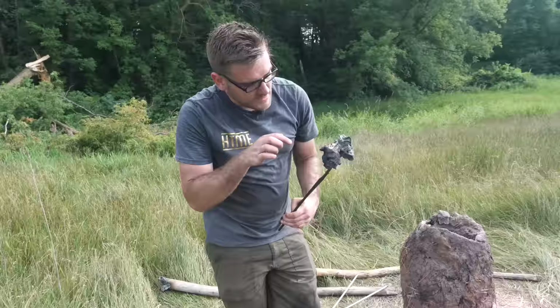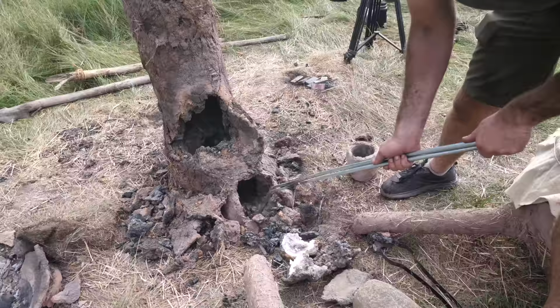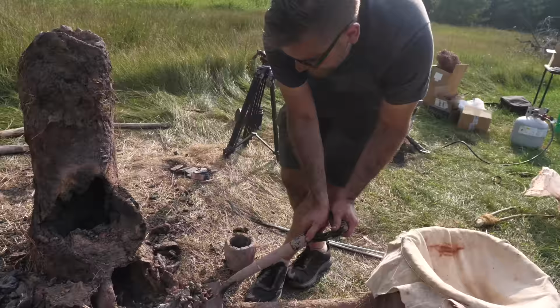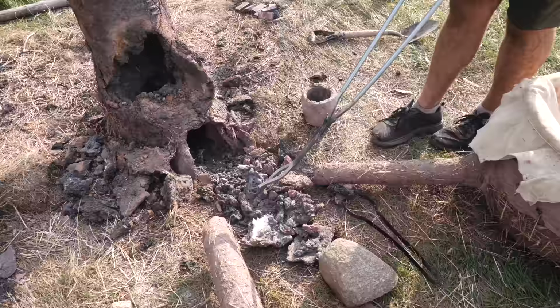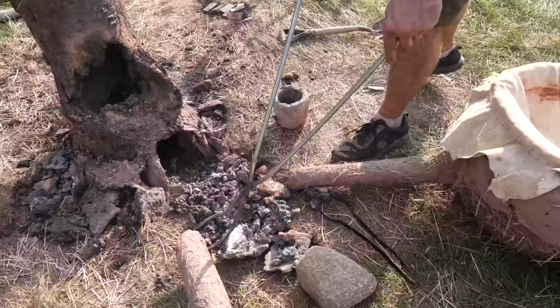Partially formed glass, and it seems like it mostly succeeded at making more of a glaze, which was the precursor to glass. So almost. It's a shiny turd. Glass, but mixed with a lot of impurities. It's close, but not quite there.